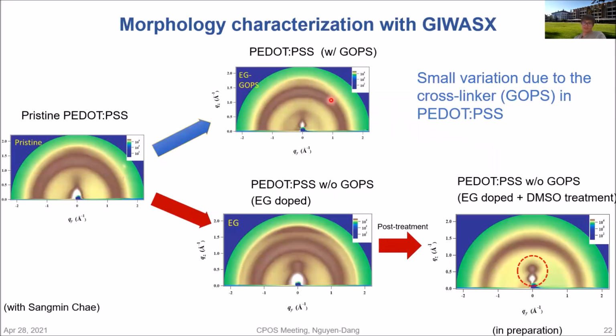So to understand why we have this higher performance, I would like to thank Sangmin for conducting the morphology characterization with GIWAXS. So the blue curve here is my devices with GOPS. The characterizations of Sangmin showed that GOPS has cross-linked the PEDOT:PSS, and he also did AFM characterizations, and he didn't see any big change in morphology of the PEDOT:PSS with different treatment. So we hypothesize that the GOPS has cross-linked the PEDOT:PSS, and it makes it very difficult for the chemical treatment to alter the properties of the material. So with GOPS, we can already define the performance of the PEDOT:PSS at the beginning, and then the fabrication technique would not alter this figure of merit.